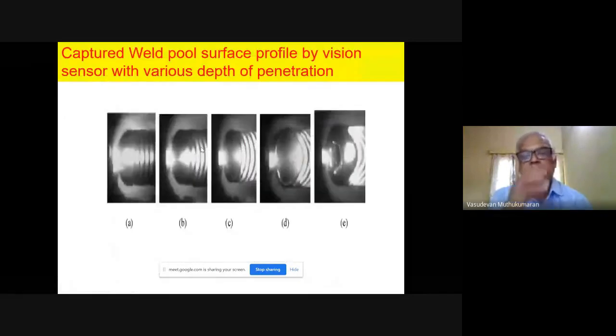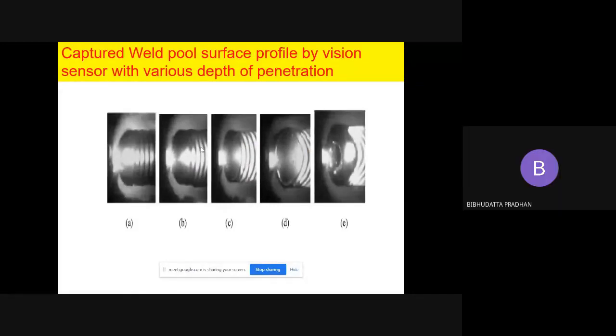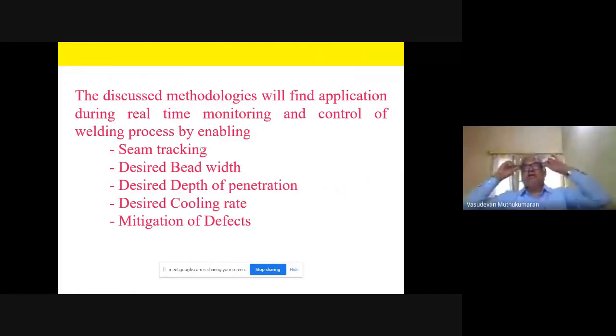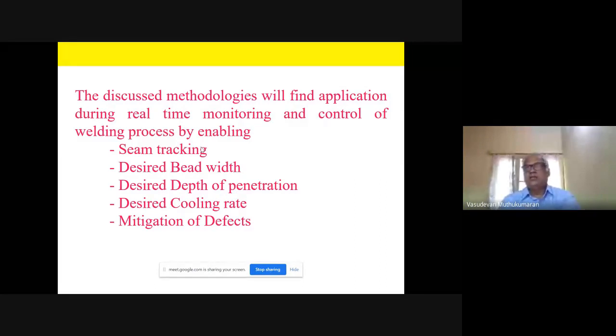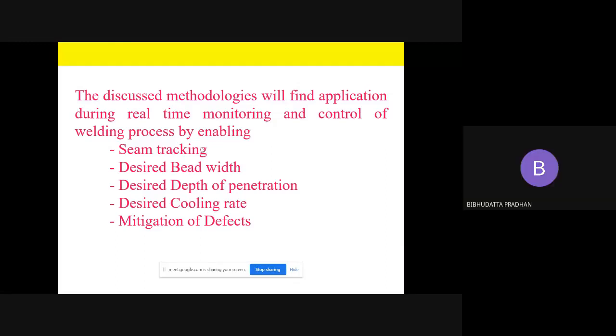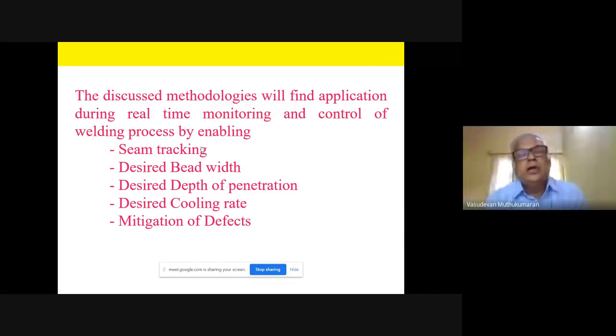We can use the surface profile for calculating the depth of penetration. This can be captured using any vision camera. So what we want to do using this intelligent welding strategy is, in real time, adopt this for monitoring and control of the welding process, mainly the TIG welding process. This can be extended to laser welding as well, for enabling seam tracking, to achieve the desired weld width, the desired depth of penetration, the desired cooling rate, and to mitigate defects in your weld. So this is a strategy we want to adopt for developing remote welding technology for our reactor components,